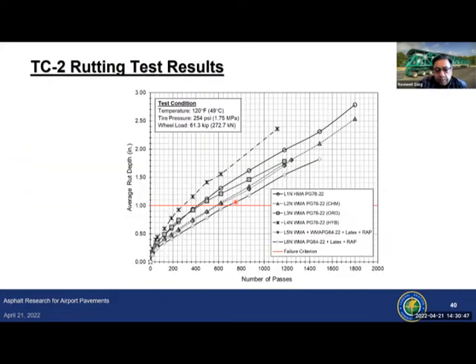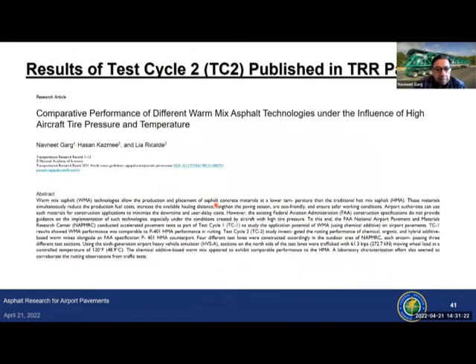This chart shows the high temperature rutting performance. And as you can see, this is a control lane, the line with circles, P401 HMA. The one with organic additive, the Sasobit, showed very similar performance. The one with chemical additive, Evotherm, showed slightly better performance. And the two lanes that had RAP included, of course, RAP is a stiffer material, so we saw better rutting performance. This red line that you see, that's our failure criteria, 1 inch of surface rut. And the findings from these high temperature rutting tests are published in this TRB paper that was published in 2021.